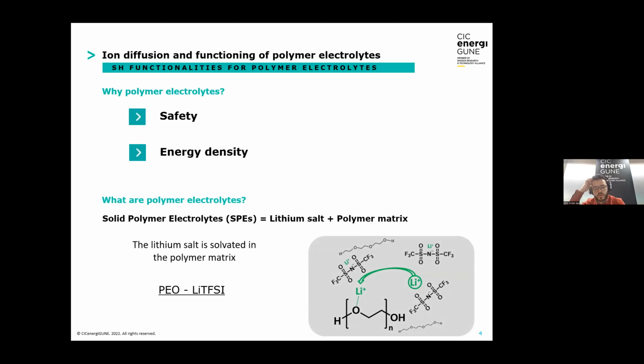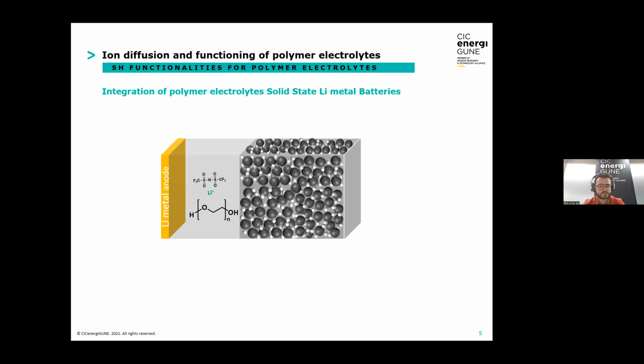So what is a polymer electrolyte? As you all probably know, a polymer electrolyte is comprised of one or more lithium salts and one or more polymer matrices, and this lithium salt is solvated in the polymer matrix. A typical example is polyethylene oxide with LiTFSI, where the lithium cations are coordinated by ethylene oxide groups, and both the lithium cations and TFSI anions are mobile through the polymer matrix.